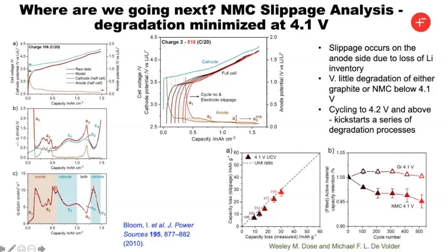In addition, you can pull out the loss of capacity from both the anode side and the cathode side. And you can see that the anode maintains its capacity in the sense that you don't have to compress the fraction that you use from the anode. And the same thing for the NMC at 4.1, again, the scaling factor remains the same. So it per se is not degrading substantially if you only go to 4.1 volts. What's happening is you're tying up the lithium in the electrolyte so that you no longer access as much of the cathode as part of this process.